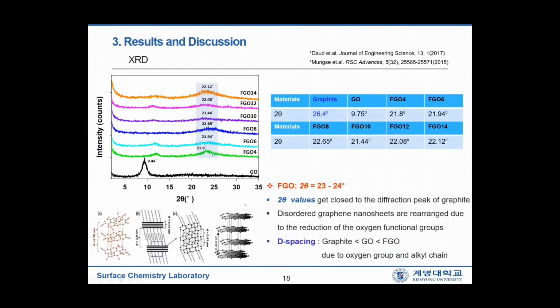These are a series of XRD patterns taken for graphene oxide and functionalized graphene oxide samples. You can see the characteristic peaks at 2 theta values from 23.2 to 23.8 for FGO samples. These 2 theta values get close to the diffraction peak of graphite. This means disordered graphene nanosheets are rearranged due to the reduction of the oxygen functional groups.